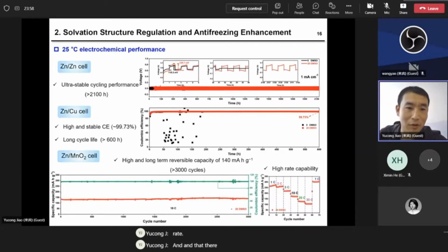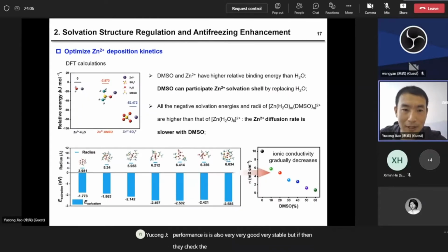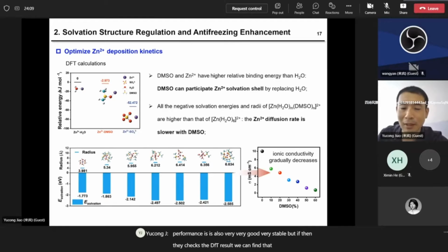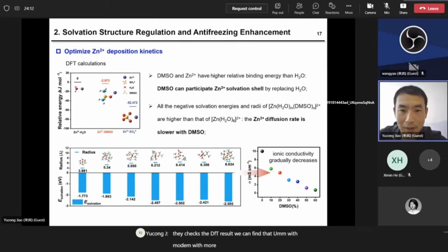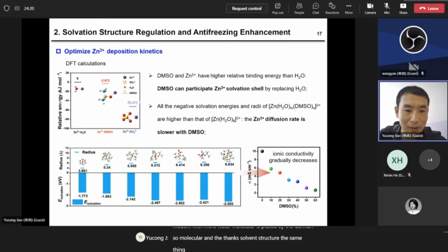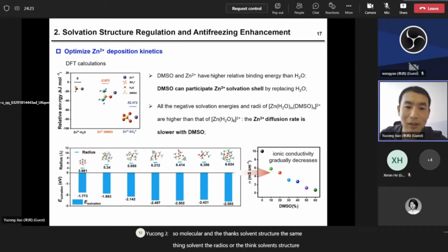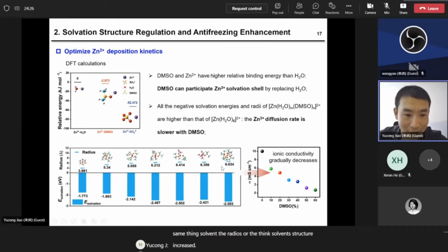And thereby the cycling performance is also very good, very stable. But when we check the DFT result, we can find that with more water molecules replaced by DMSO molecules, the radius of the zinc solvent structure increased. And with the radius increased, we can see that the ionic conductivity gradually decreased. So this means that with this kind of additives, they can improve the cycling stability.